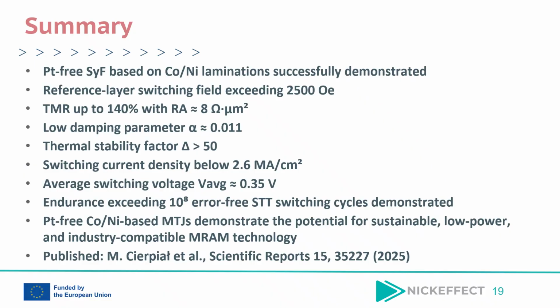In summary, the NICKEFFECT project successfully demonstrated the feasibility of PT-free MTJ technology based on cobalt-nickel synthetic ferromagnet multilayers. The developed SyF system provided strong stabilization of the reference layer with switching fields exceeding 2500 Oersted. After optimization of the complete MTJ stack, excellent electrical and magnetic performance was achieved, including TMR values up to 140%, RA values around 8 ohm micrometer squared, low damping parameters close to 0.011, and thermal stability factors exceeding 50.